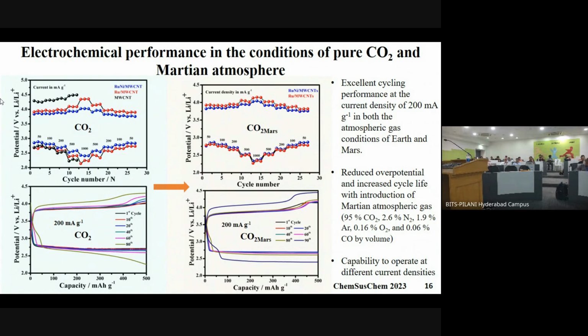What we see here from this cyclability is that, compared to the multi-wall CNT, the black dotted curves, with ruthenium multi-wall CNT and ruthenium nickel multi-wall CNT the overpotential between charge and discharge is minimized when we use the ruthenium nickel multi-wall CNT. And also in terms of capacity with respect to different current densities, we go from the first cycle to the 80th cycle, and we see, of course, that with cycling the overpotential increases, but the system is stable up to 80 cycles.